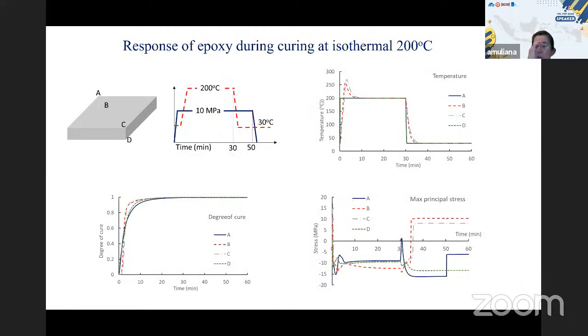So here, for example, we show curing at isothermal 200 Celsius. The curing also involves applying pressure, which is 10 megapascal, and heating to cure temperature. Now, what we want to show here is the non-uniform curing process. So we randomly pick different locations. When you look at this degree of cure, right, they don't cure at the same time. So this variation actually gives us a significant amount of stress, as you can see here. While the pressure is 10 megapascal, if there is no additional stress, it should stay within this 10 megapascal. Because of this non-uniform curing, you'll see these changes in the stress as you heat it up.